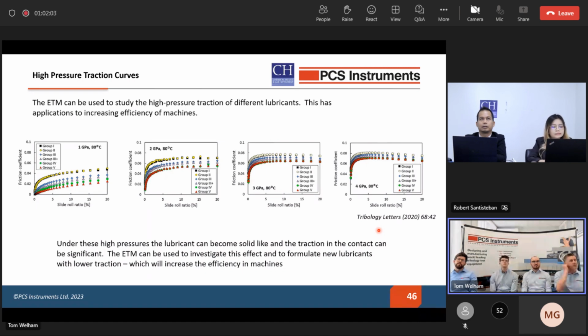We can see the initial slope of the curves increases significantly as we increase contact pressure, and we also arrive at a much higher traction coefficient at significantly lower slide roll ratios, as we'd expect. The rapid rise in the traction coefficient at low slide roll ratios in these high pressure charts is very significant. Rolling element bearings don't operate in pure rolling. Typically for deep groove ball bearings, for example, we have a small amount of sliding, between 1 and 2% slide roll over much of the ball and raceway contact. And this can be higher in other rolling bearings.